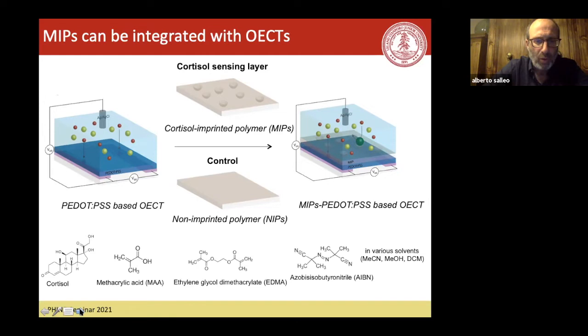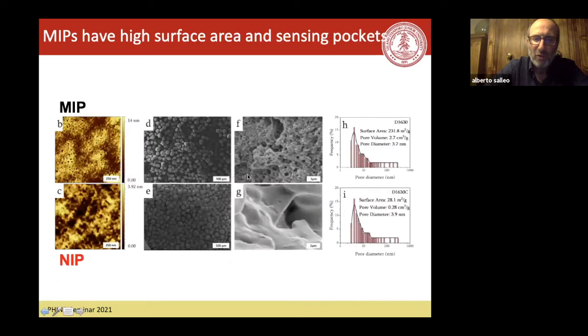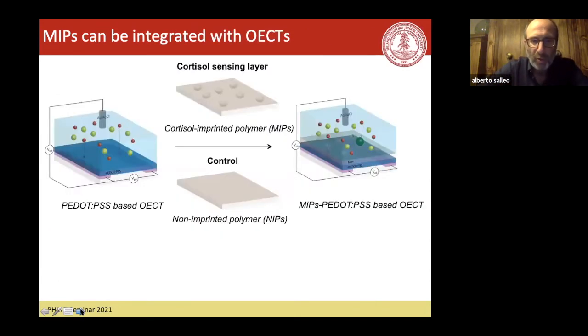So here's our recipe: cortisol, this is the monomer, this is the cross-linker, and this is called the initiator, which initiates the cross-linking. And a very important part of this is the solvent, because you need a solvent that allows you to make these high surface area polymer particles. So you need what is called a porogenic solvent. And this is actually pretty messy, because the way you make this molecularly imprinted polymer is it's quite brittle. You make it in a vial, and then you break it and grind it into these particles. And then these particles are integrated in a membrane similar to the one that we use for ion sensing. So the PVC membrane has these particles dispersed in it. And there's probably a lot of engineering that goes into optimizing that. We haven't really attacked that quite seriously.